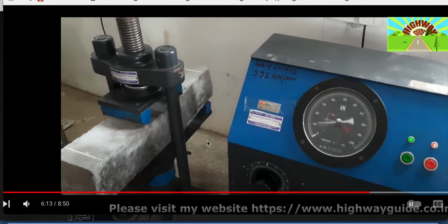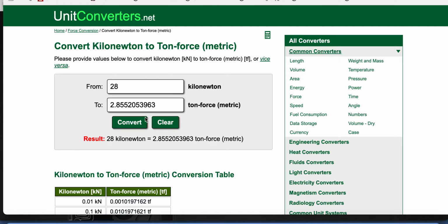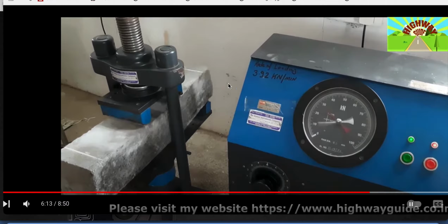This will be a shear test, tension test, correct? Yeah, I said shear test out here. Tension test, its flexural ability. It's already failed. It's at 28 kilonewtons, approximately 29 kilonewtons. If you need to know what that is, you come over to a scale. You can type in 28 kilonewtons. I like converting to ton force, and I don't have to do any more fancy conversions. It's 2.8 tons based on this loading.